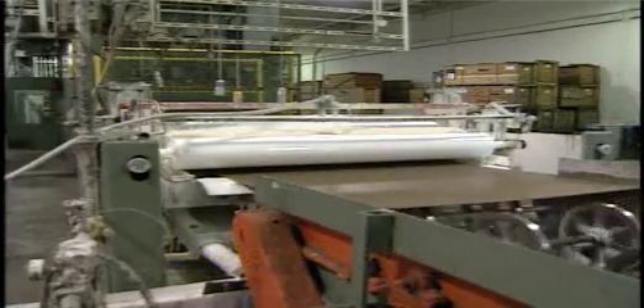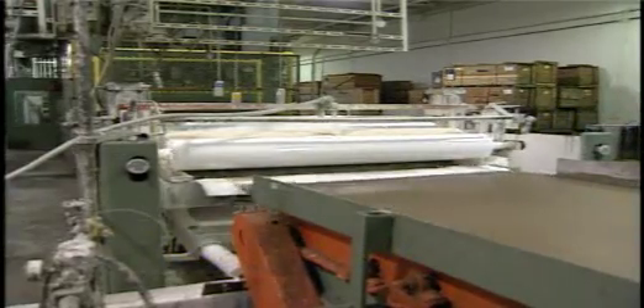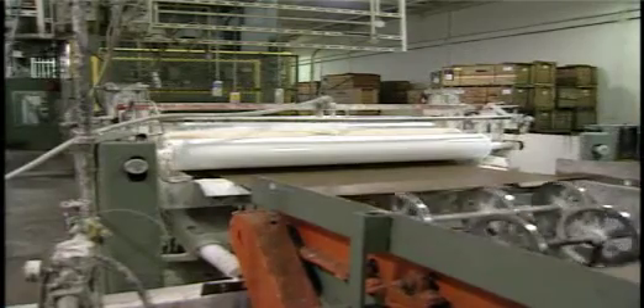Roller coating involves the transfer of a coating from a trough or vat to a flat surface by a series of rollers. Roller coating machines typically have three power-driven rollers. One roller runs partially immersed in the coating vat and transfers the coating to the second roller. The strip or sheet to be coated is run between the second and third rollers and is coated by transfer of the coating from the second roller. The distance between the rollers determines the amount of coating that is transferred.